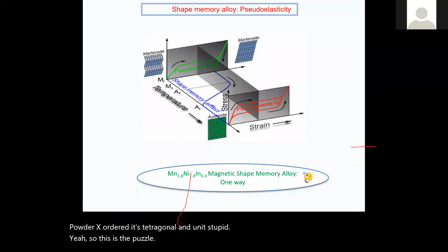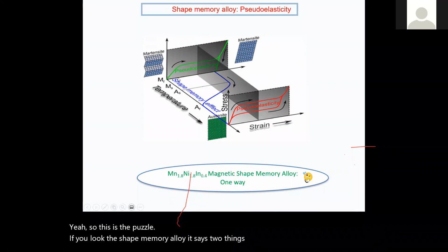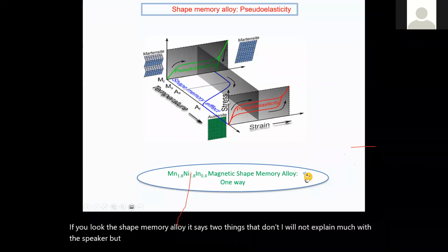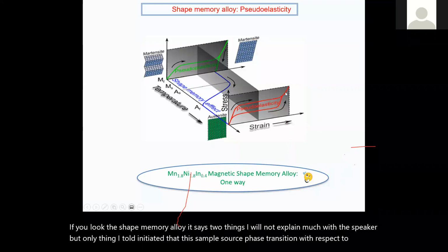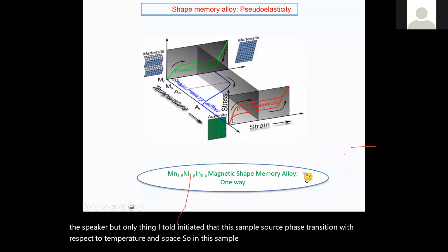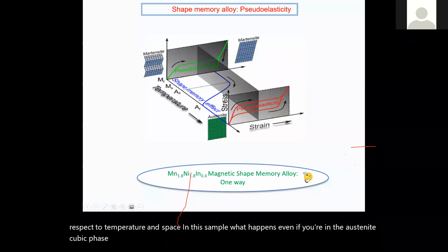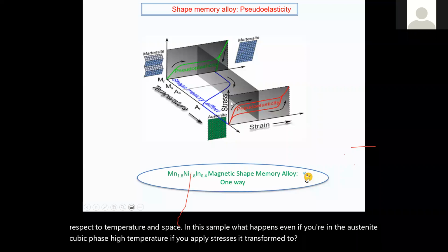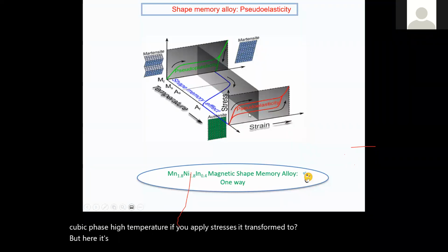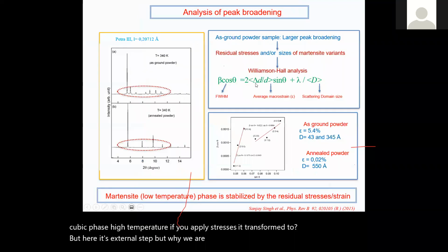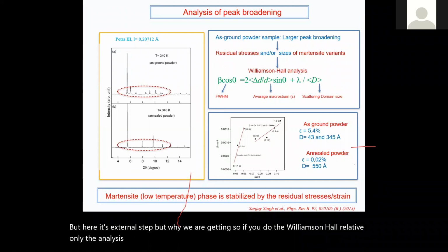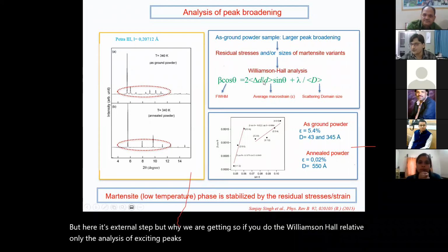But if you look at the shape memory alloy, it says two things. I will not explain much with this figure, but the only thing, as I told initially, is that this sample shows phase transition with respect to temperature and stress. In this sample, even if you are in the austenite cubic phase at high temperature, if you apply stress, it transforms to the tetragonal or lower symmetry phase. But here it's external stress. So why are we getting that? If we do the Williamson-Hall analysis, meaning only the analysis of XRD peaks of both the XRD patterns, you get the following.